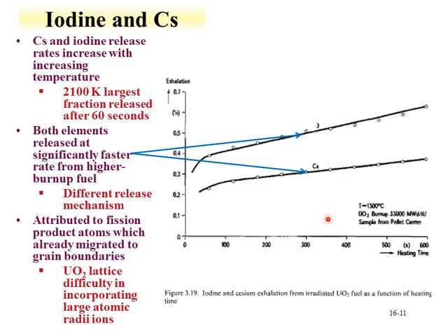Here's an example of uranium burnup at 33,000 megawatt days per ton of uranium. And we see that for the release of iodine and cesium, there's an initial increase and then the release reaches a constant rate as a function of time. There are somewhat different mechanisms for release, and these relate back to the behavior of the fuel, particularly any damage that was done due to higher burnup.